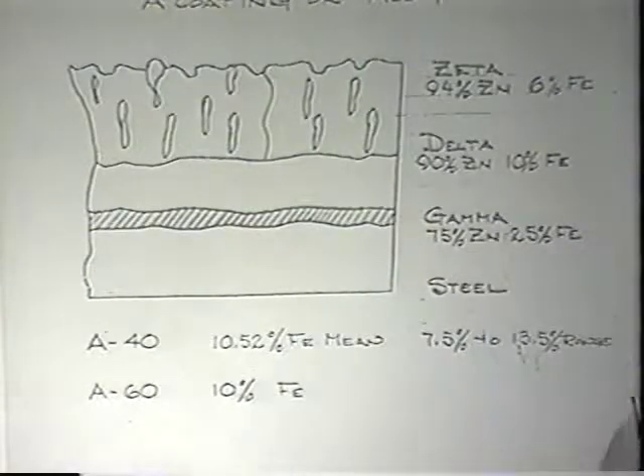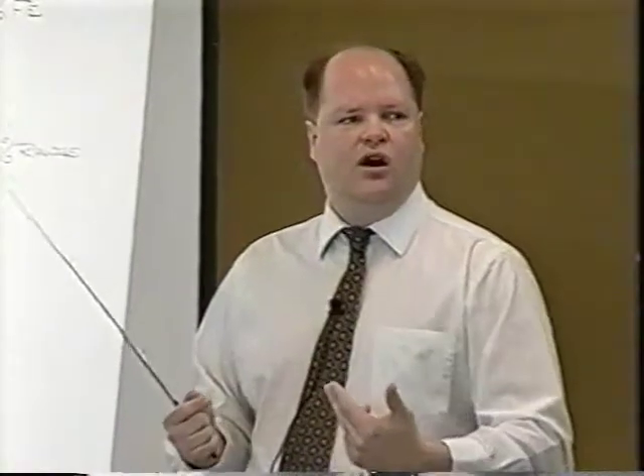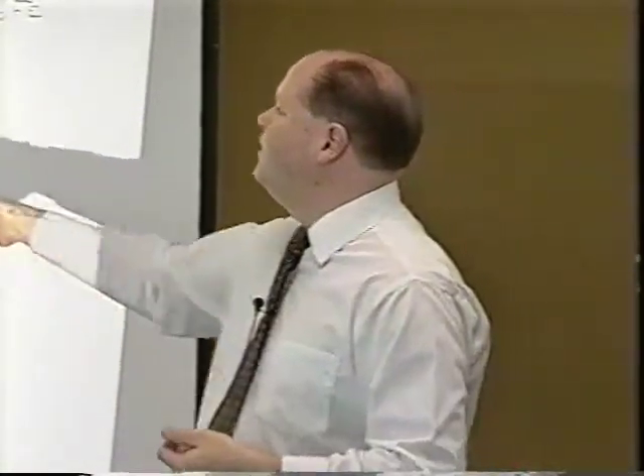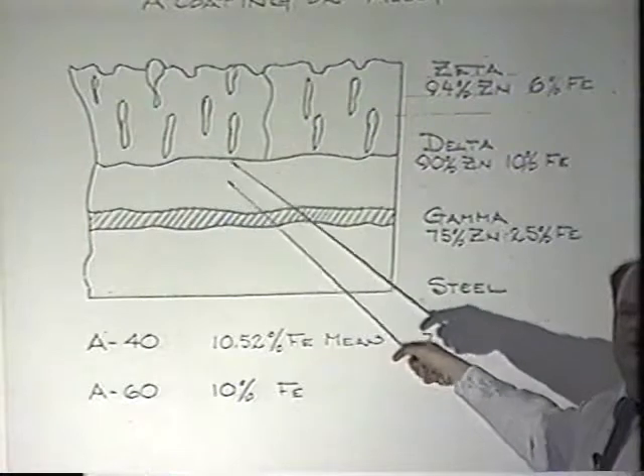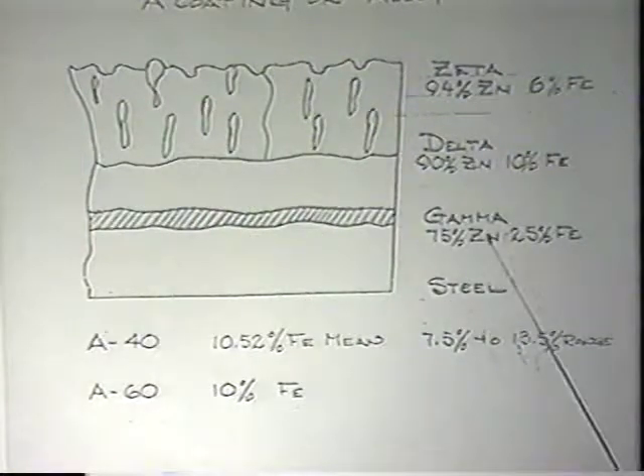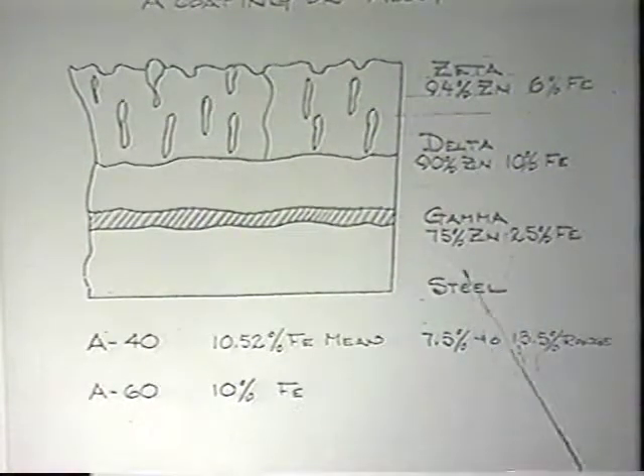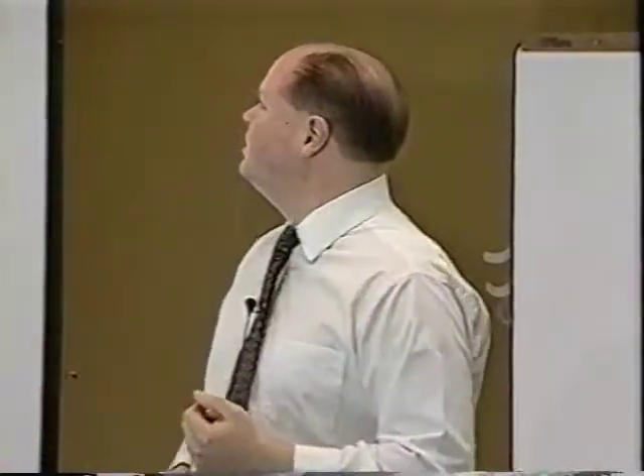So if you have a severe bend or a severe draw, you may start getting some of this coating flaking off because now you have an alloy that's kind of brittle. Whereas in galvanized, you can bend it all day long and for the most part it's not going to come off. So there's a drawback to it. If you've got something that's a big draw or high forming part, probably this isn't the way you want to go. If you've got something that's a fairly easy draw but you need weldability and paintability, maybe this is the way to go. So there are advantages and disadvantages of either one.